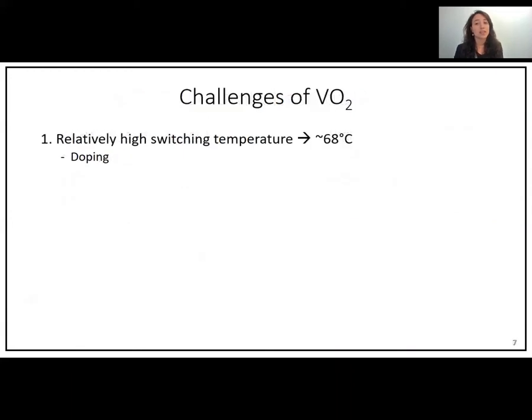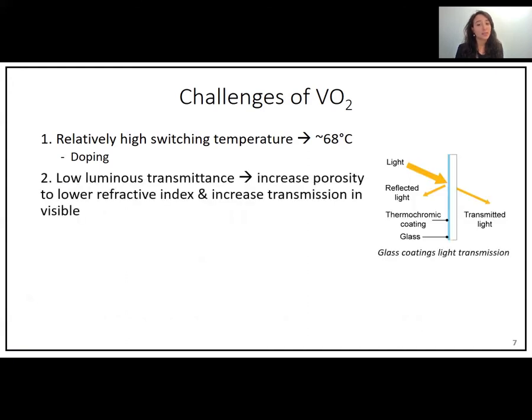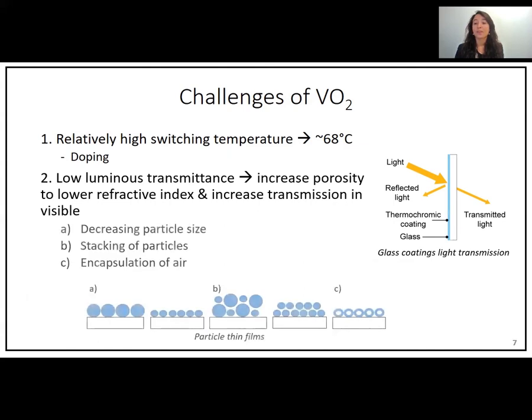There are various challenges in the application of VO2 to windows. One of the main ones is the relatively high switching temperature of around 68 degrees, which is not ideal for a smart window. This can be resolved, though, through doping of the structure with different elements. The second challenge is that the luminous transmittance is low. This means that the coating is not completely transparent and has a tint and is undesirable for windows. This can be approached through decreasing the particle size, or by stacking of the particles, or by encapsulating air. This is all to avoid light scattering.